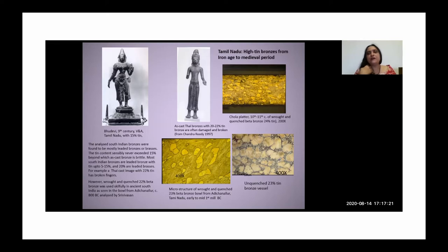And just above, this is just to point out that this is actually a tradition that carried on in the Chola period as well. So though they were making the cast leaded bronzes, they seem to have been aware of what to do with the high-tin bronze phases and how to exploit them. So what you're looking at on the top is actually a platter from the Chola period, which is in the Government Museum Chennai, which I had sampled. And that's of the 10th, 11th century. And that is a wrought and quenched beta bronze with about 24% tin.